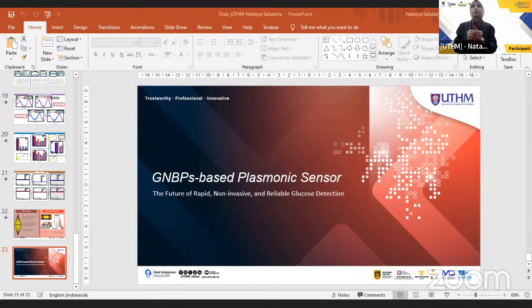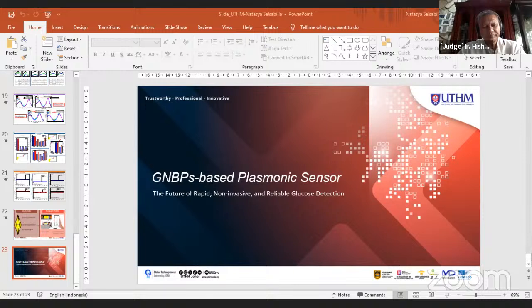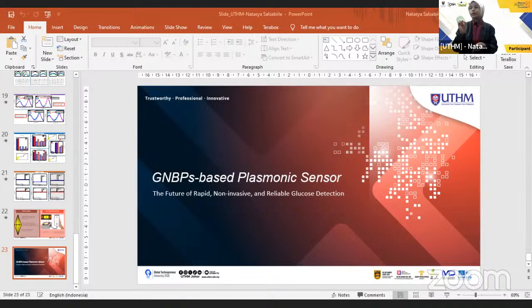So we should consider what the optimum time is to functionalize the surface of gold nanobipyramids (GNBPs). Why? Because first, when we use amine groups to functionalize the surface of gold nanobipyramids (GNBPs) over a long period, it can cause a morphological change, which will cause a decrease in the sensitivity. The reason I chose gold nanobipyramids (GNBPs) is that they have a higher sensitivity response compared to other forms such as rod, rice, spherical, and so on. So when the morphology changes, of course, it will cause a decrease in the sensitivity performance.